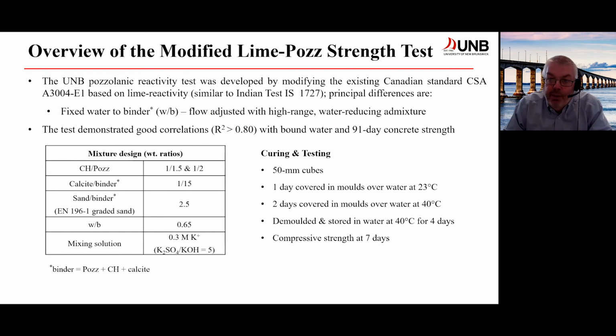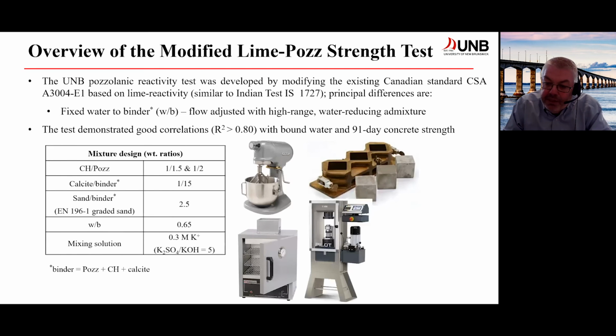So our modified lime pozzolanic strength test is basically you produce a mortar where the binder is just a combination of calcium hydroxide and pozzolan. There is no Portland cement in these mortars, so the only strength that you'll get is from a reaction between the pozzolan and the lime. I don't have time to get into the details of the test. The idea of this test was to make it simple. One of the Rilem tests requires access to a calorimeter, which most labs don't have. We wanted to develop a test that most current materials testing labs could run. You need to be able to make mortar cubes, and you need an oven and a cube crushing machine, and pretty much you're good to go.